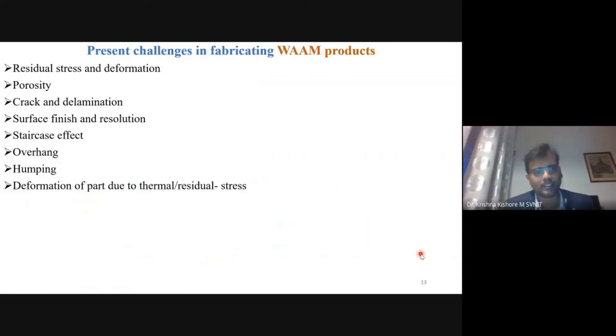However, as I discussed, there are some challenges like residual stresses, deformation or porosity in the case of some alloys, and crack delamination. When the porosity is there and residual stresses are there, obviously there will be some cracks and delamination happening. And in the case of WAAM processes, one important thing is the surface finish. So post finishing is obviously required for the WAAM process. Actually we are depositing layer by layer, and at the end, to maintain the aesthetic look of the component, we will be doing some kind of surface finishing operations. In order to control these things, a lot of research is going on in this direction, and people are developing pulses and different path planning strategies to control this kind of surface finish effects. There is a staircase effect, we will see this one, and humping and overhang effects are also there in the case of WAAM products.